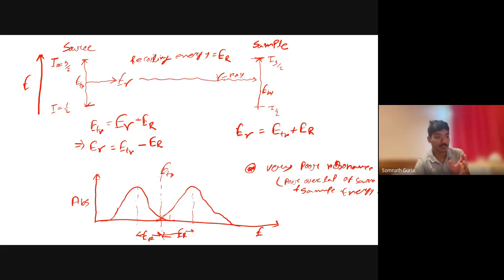He started to look at this phenomenon with a source and sample in a particular way that people are actually using, and then he started lowering down the temperature, and he is getting some data. A very good overlap has been found between the source absorbance versus energy curve and the sample absorbance versus energy graph. They found a very good overlap.